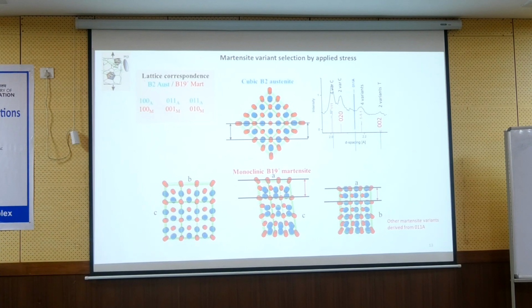And this is my video which demonstrates, with animation, how to analyze this diffraction pattern, and I will be talking more about it later. So here is an example of a typical diffraction pattern around the 011 austenite direction, because this reflection is very intensive in X-ray. If you do the X-ray evaluation of martensite, you will typically see such a pattern. And then you don't know what is what, but in fact it can be analyzed with this animation. So whenever later on you have this problem, please go and play this animation.